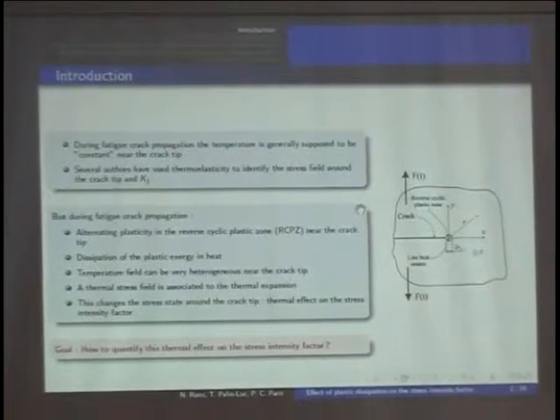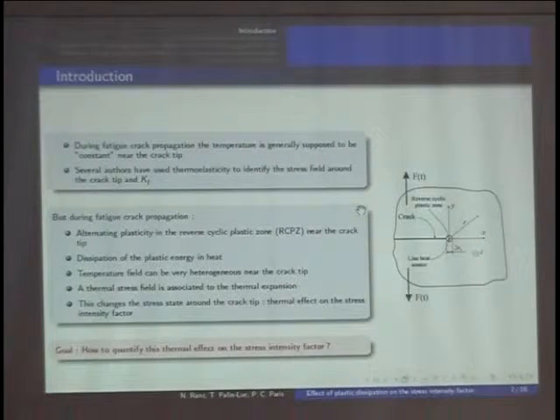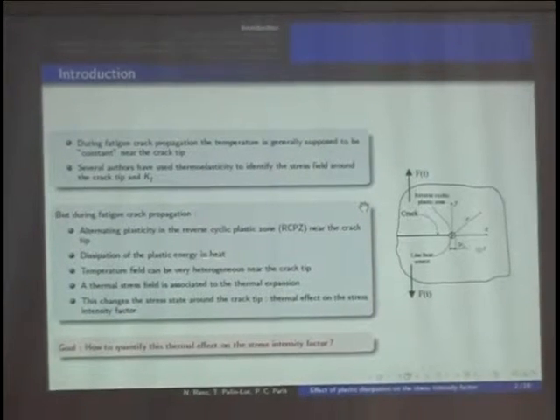So what is the motivation of the work? All of you know, of course, that when a crack is propagating, many people use thermoelasticity to estimate the stress field around the crack and to compute the stress intensity factor. Many people consider that the temperature around the crack tip is constant. But if there is crack propagation, all of you know that there is alternating plasticity in the reverse cyclic plastic zone. So one significant part of this plasticity, I mean strain energy plasticity, is dissipated in heat around the crack tip.